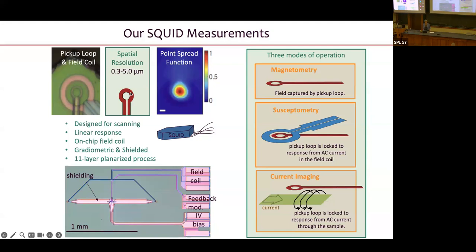Our smallest are about 0.3 microns, 300 nanometers. Some people make some using a completely different technology called squid on chip that are as small as 100 nanometers. And so if you imagine taking this loop and you're measuring the total magnetic flux through the loop, imagine that this loop is fabricated on the edge of a chip.